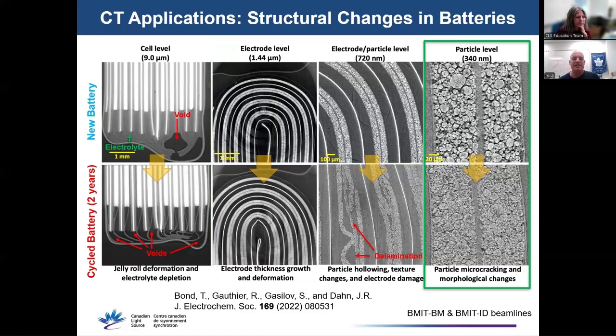On the far right, even higher resolution measurements illustrate differences in particle morphology and microcracking of individual particles within the electrode layer after cycling. And if you look really closely, a lot of the particles in the cycled battery at the bottom right here look kind of crushed. This is because the cycling has caused a lot of expansion and contraction, which eventually damages these particles. And this again can cause a battery to lose capacity or fail in the long term.